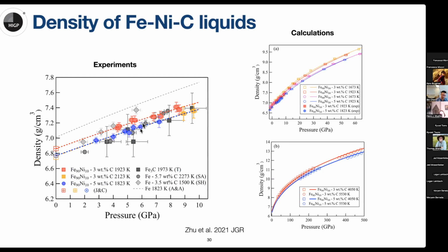From our work, we can see that by increasing the amount of carbon, we see a lower density for the iron nickel carbon liquid. But our experimental result is only up to about 8.5 gigapascal, which is still far away from the Earth's liquid outer core. So we also performed first principles molecular dynamics calculations to extrapolate the density determination of those iron nickel carbon liquids to higher pressure.